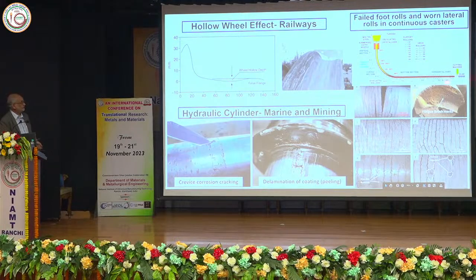So the first case is continuous casters. You're pouring hot metal at around 1400-1500 degrees, and then you have rolls through which it passes and you extract heat. You open the gate here, the tundish opens and the hot metal flows. This is where you're seeing the maximum temperature, and this is where you're also incidentally seeing the maximum corrosion, because they are covered with fluxes which are chlorides and fluorides, one of the most aggressive compounds you can think of.